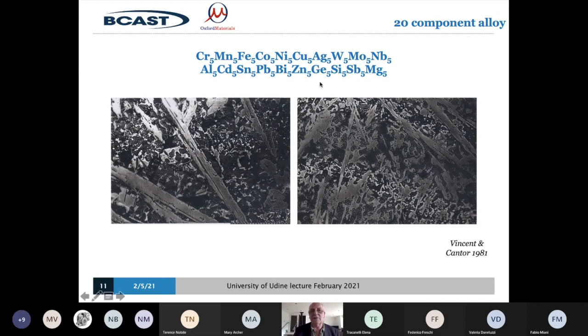And I show you this one because until very recently, this was the world record in the number of components added in an alloy. This is 20 components with 5% each. And we made that material up, and the truth is it was a mess. And this is the microstructure of it in a microscope, and it consists of lots of different crystals in a big jumble. Perhaps you might say, not very interesting. However, we discovered very quickly that it was indeed interesting because this background black area is what's now called the Cantor alloy.